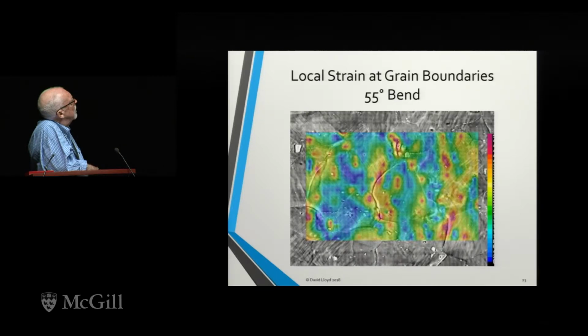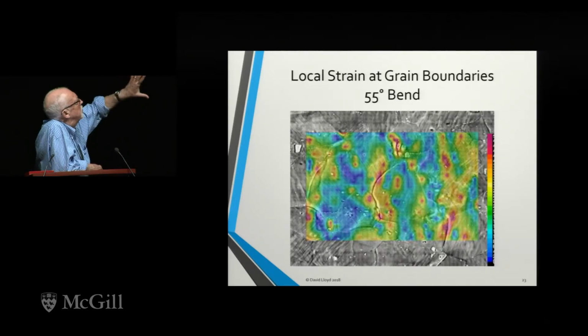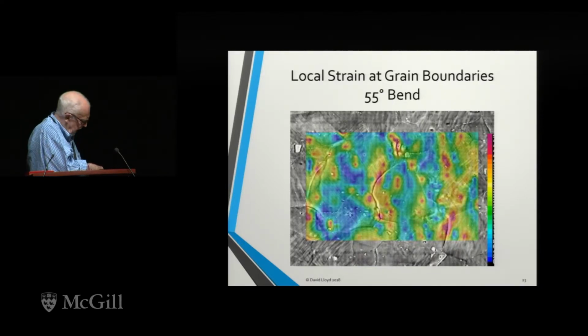This is a strain map that I've superimposed over the microstructure underneath. It's a 55-degree bend angle again, which is the same as the SEM FIB shots that I showed you earlier. You can see the boundaries here. Red is the high strain regions, and then it goes down to the blues where the strain is relatively low. Obviously, the deformation, not too surprisingly, is incredibly inhomogeneous.